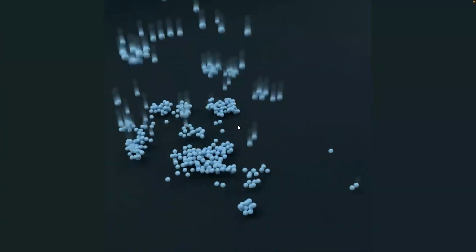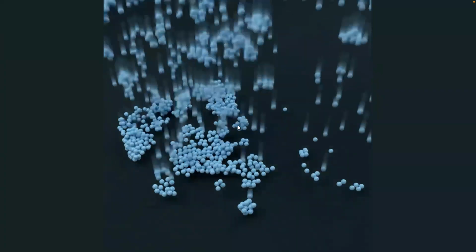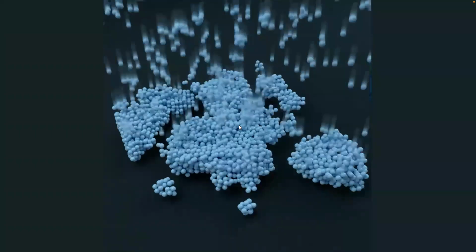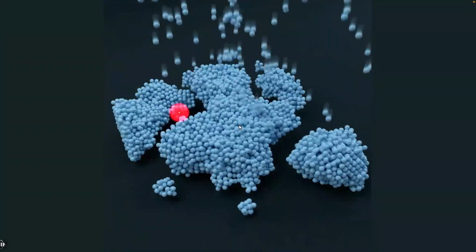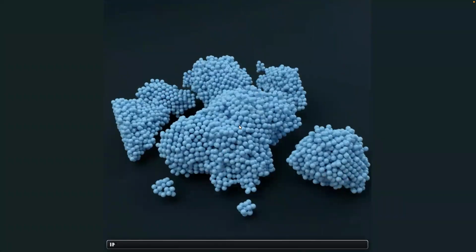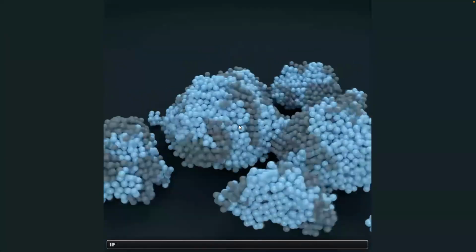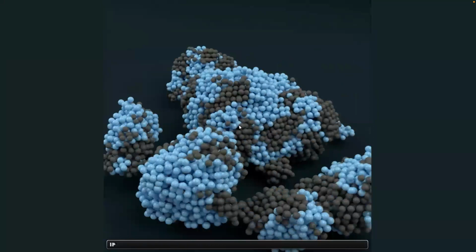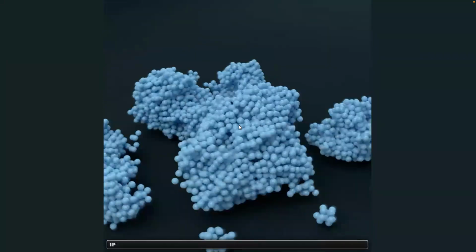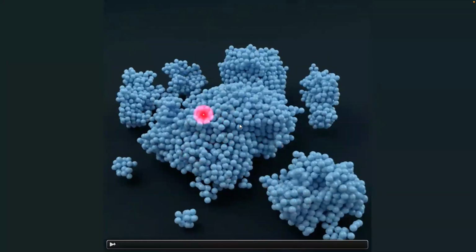Features, or there's no crystallinity. But if you notice here on the top and on the surface, we're starting to see some ordering, the nucleation that happens on the surface, and that's not unexpected. I'm rotating the system here, and I will uplift the crystalline atoms, and you'll see that at least within the inside of the crystal, it is fully amorphous.